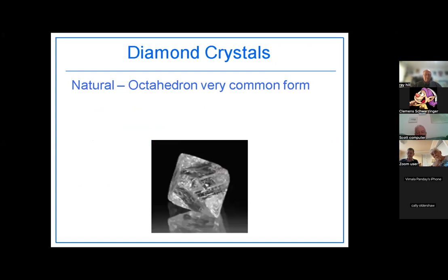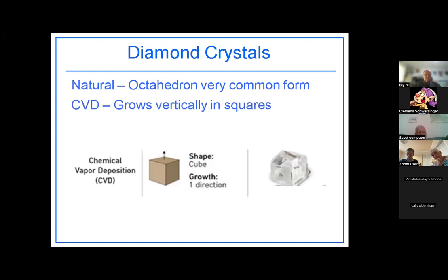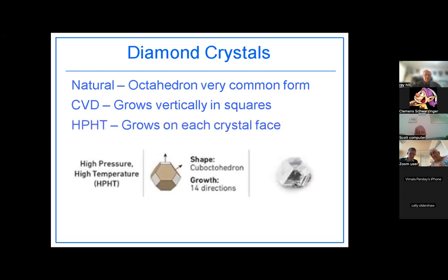Okay, as far as diamond crystals, your natural diamonds are frequently found as octahedrons. This was the predominant diamond shape of the early diamonds coming out of India. They would find these perfect little octahedrals in the alluvial deposits. Now the CVD, it grows vertically in the squares, as you can see here. So basically it grows from the bottom up, like in that middle video or picture. HPHT, here you go, the cuboctahedron, and it grows on pretty much all the sides.